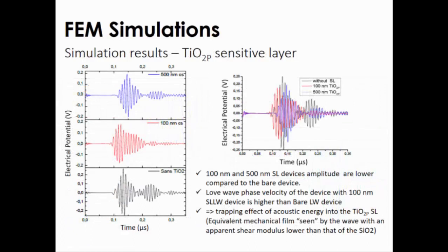Here, addition of titanium dioxide porous layer: without porous layer here, 100 nanometers, 500 nanometers. The superposition here shows that the amplitude of the wave decreases with the addition of the layers. But an interesting thing is that we have between the device without sensitive layer and the device with 100 nanometers, a modification of the Love wave velocity, which is higher in the device with 100 nanometers. This is not a typical response due to mass effect loading. The interpretation is that a part of the acoustic energy of the guiding layer is trapped inside the mesoporous guiding layer. So it's what we want to do.